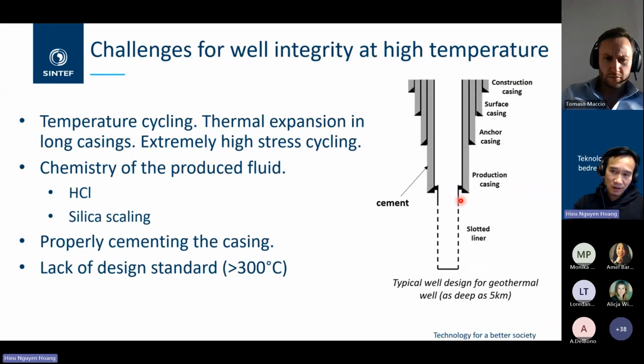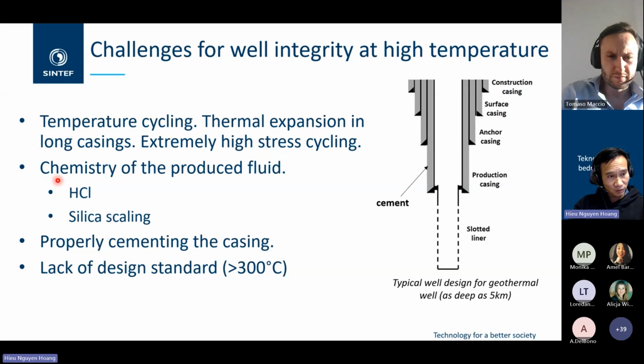And operating at high temperature conditions introduces a unique challenge for well integrity, because we have temperature cycling, introducing thermal expansion and leading to high thermal stress in the casing and cements. And we have nasty chemistry from the produced fluid, including hydrogen chlorides, and this is very detrimental for casings, leading to serious problems related to corrosion and scaling that we have seen in many wells in the past.